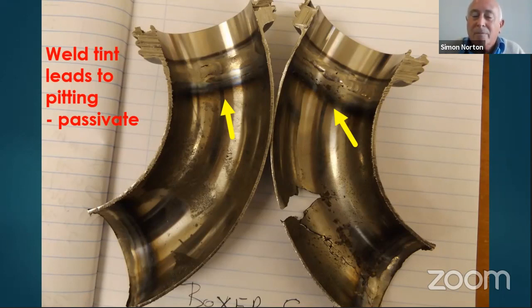But if they shield this correctly, there'll be no heat tint there, and then they will have a proper weld. If it's looking like this, if they now go to their failed pipes, cut out the samples that have failed, slice them open, and if they look like this, then they've got problems, and then they need to consult. They must start purging. They must start shielding their system and purging the system. There are actually photographs that can tell you the level of oxygen. I think in this particular case, I could almost tell that there was something like 500 ppm oxygen in the pipe just by the color of the weld and just by the color of this heat tint.